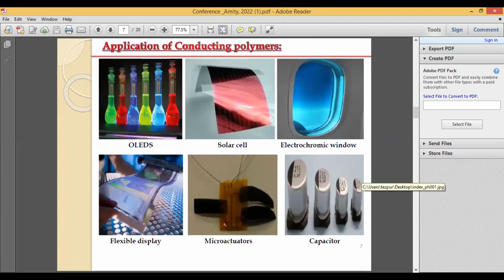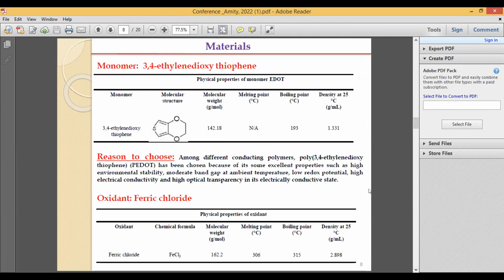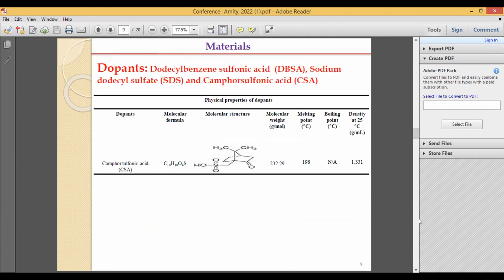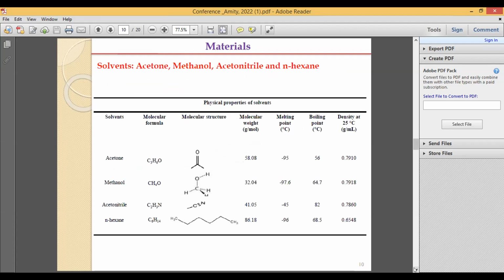These are some applications of conducting polymer nanostructures: OLEDs, solar cells, electrochromic windows, capacitors, microactuators, and flexible displays. And here are the materials I have chosen. As monomer, I have chosen 3,4-ethylenedioxythiophene. I have taken FeCl3 as an oxidant, and camphorsulfonic acid as a dopant. This camphorsulfonic acid forms the micelle and guides the formation of the nanostructure in our case. These are the solvents that I have used: acetone, methanol, acetonitrile, and n-hexane, to remove unwanted product from the synthesized nanostructures.